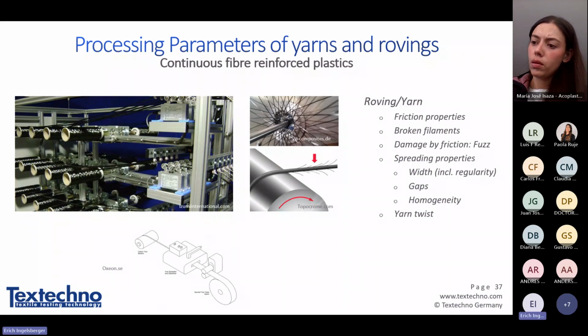Now I would like to come to a testing instrument, which we again have created with some industrial partners. The background here is what happens during the processing of a roving. There can be some negative effects during processing. For example, if you use such a creel here, where you apply a lot of rovings and then you pull off or strip off the yarn from this roving, you may have some friction along guiding elements, which can, as you can see here, create breaks of the individual fibers or filaments. So everywhere where you have some surface, you can get some fiber breakage, for example, or some effects which might disturb during a production.